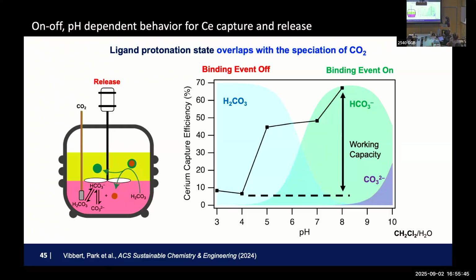That's what you do. As you can see, this is not an environmentally friendly system at all. So when we designed this system, we really wanted to make the pH range just right here. If you work on CO2, you should know why we are targeting this and why we are excited about it. Because this is the CO2 hydration, right? So what we are proposing to do was we bind metal at pH 8. If you bubble CO2, you lower the pH, we cannot ever go down below 4, right? So we can go down here and release all the metal.